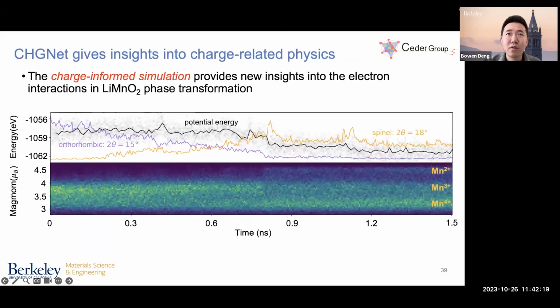So to answer this question, here's what we highlighted by the power of our CHGNet. The upper plot shows the potential energy of the lithium manganese oxide cell in the black curve, together with the orthorhombic peak intensity and the spinel peak intensity. And the lower plot shows the distribution of the magnetic moments on all the manganese ions as a function of time. You can see at the early part of the simulation, the magnetic moments of the manganese ions are mostly distributed between 3 μB and 4 μB, which correspond to manganese 4+ and manganese 3+.